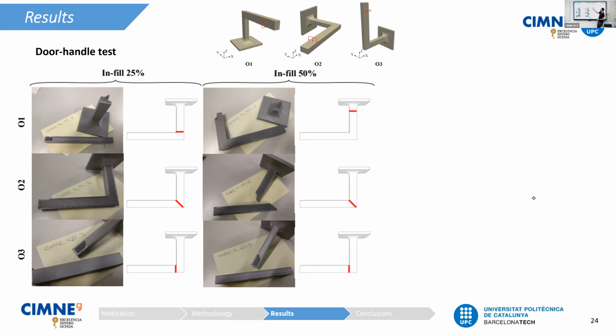When it is printed with a 50% infill density, we can see that the failure occurs at the base, even though it was printed using the same exact orientation. If we go to the second orientation, the failure occurs diagonally for both infill densities. And if we go to the third orientation, the failure occurs vertically. These are the experimental results.